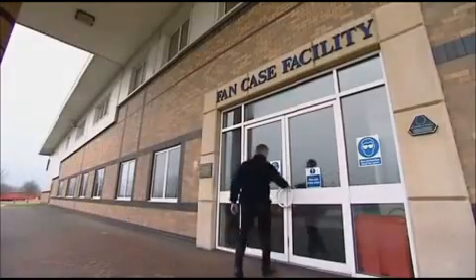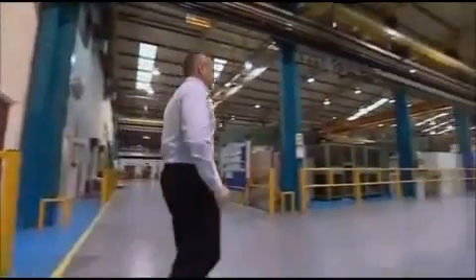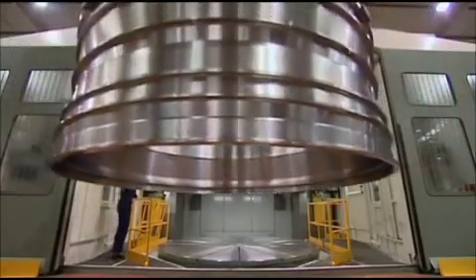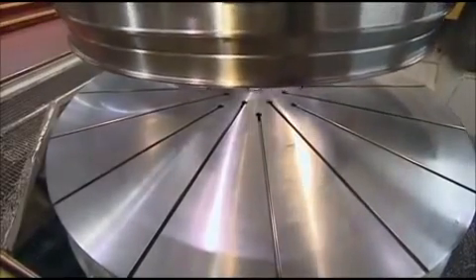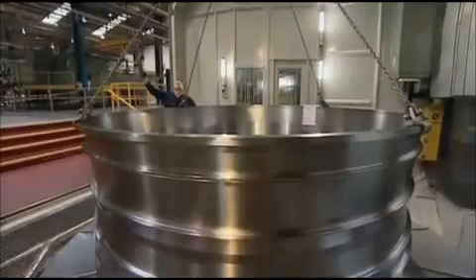The biggest single module is manufactured at another of Rolls-Royce's specialist factories just 50 miles down the M1. Mark Reid is in charge of building the massive protective case that shields every engine's fan blades. The fan case's primary function is to guide air through to the main core of the engine, and to provide a containment system in the event of a blade-off. When the forging is originally constructed, it weighs five metric tonnes — when finally finished and machined, it weighs roughly 500 kilos. We machine it down to some very fine tolerances, with typical wall thicknesses around two and a half millimetres.